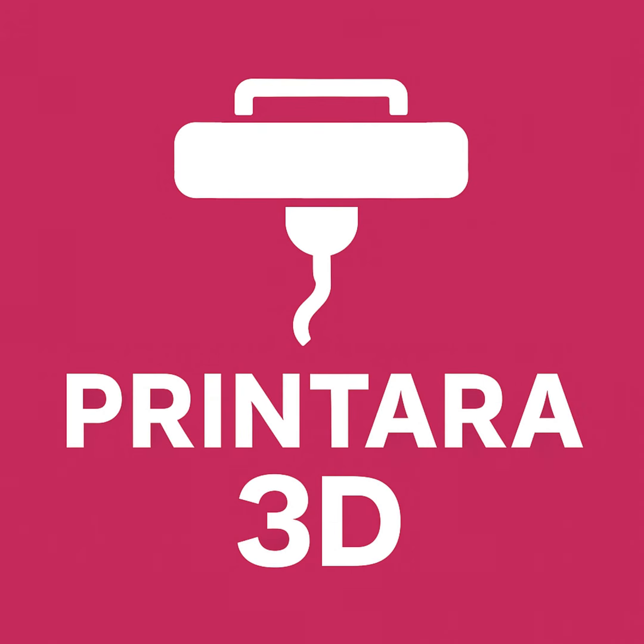I think a lot of people assume that just means you might get some ugly stringing or a few pops and hisses at the nozzle like you do with wet PETG. It is far more severe than a few cosmetic pops. We need to talk about hydrolysis. Hydrolysis, that sounds serious. It is. When you take a filament that has absorbed atmospheric moisture and force it into a hot end sitting at nearly 300 degrees Celsius, that trapped water instantly flashes into steam. And I'm guessing that steam creates microscopic voids in your layer lines. It certainly does. But the combination of intense heat and water actually triggers a chemical reaction. That is hydrolysis. Wait, so the water is actively changing the chemistry of the plastic inside the nozzle?